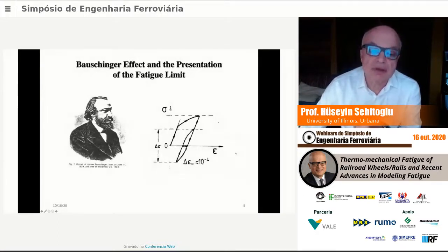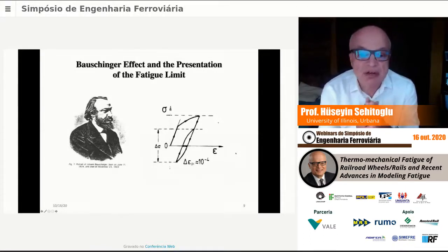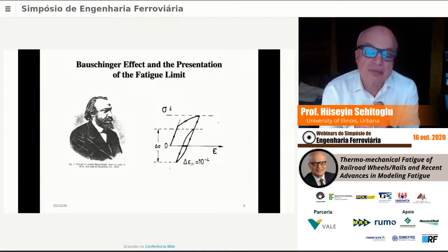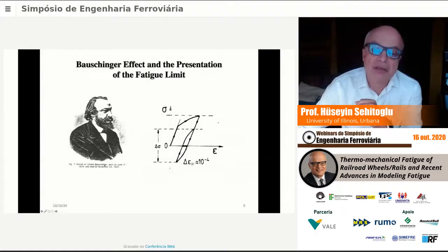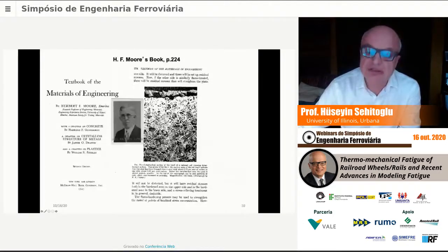So fundamentally, the fatigue phenomenon is associated with plasticity. Plasticity can occur at local scales, and Bauschinger, whose work I'm sure people are familiar with, postulated that when the plastic strain in a hysteresis loop is of the order of 10 to the minus 4, the corresponding stress range is considered to be the fatigue limit. This was something he proposed many, many years ago.